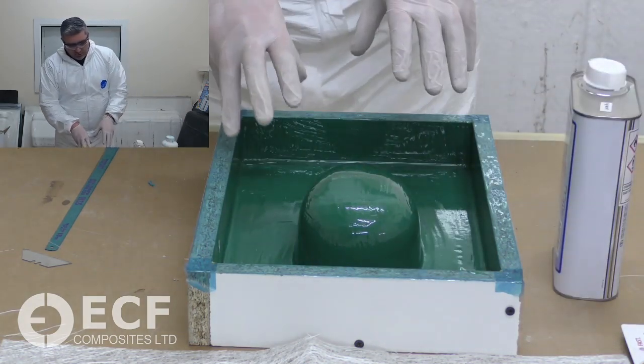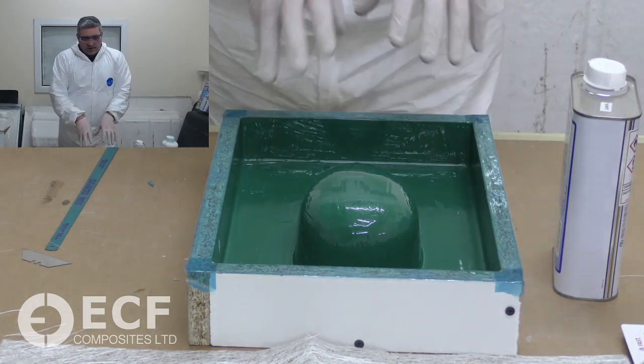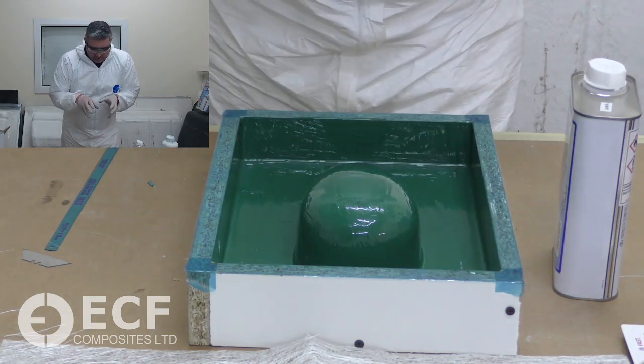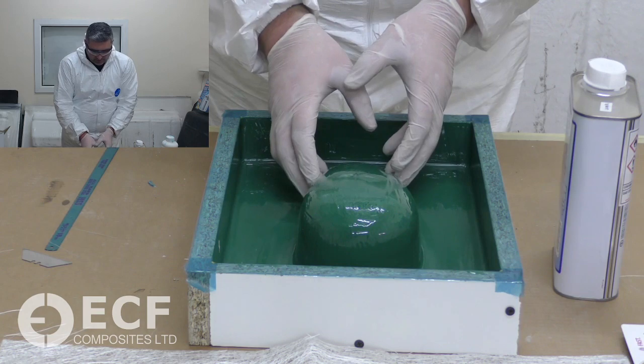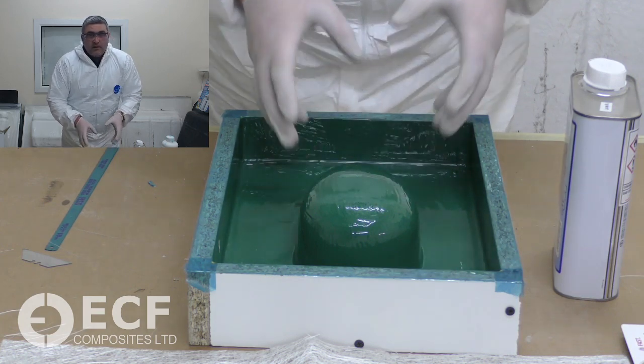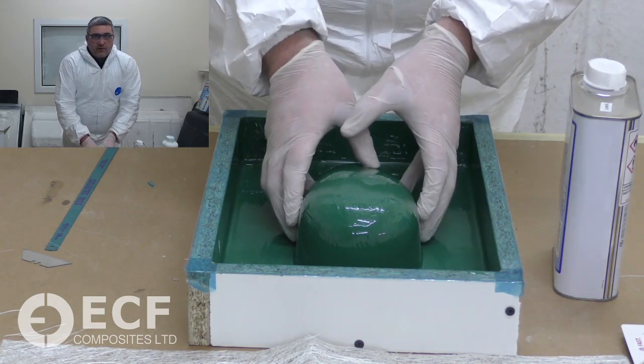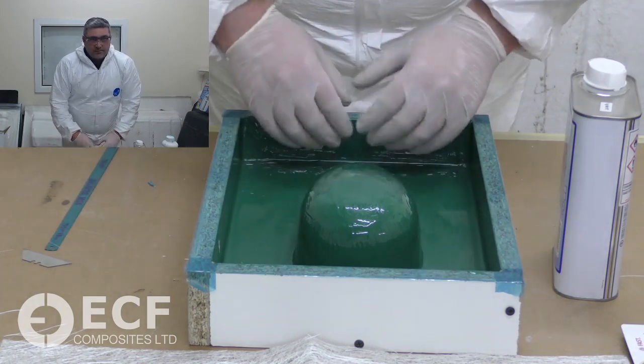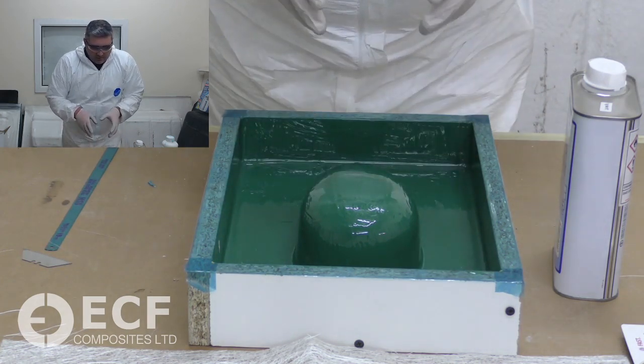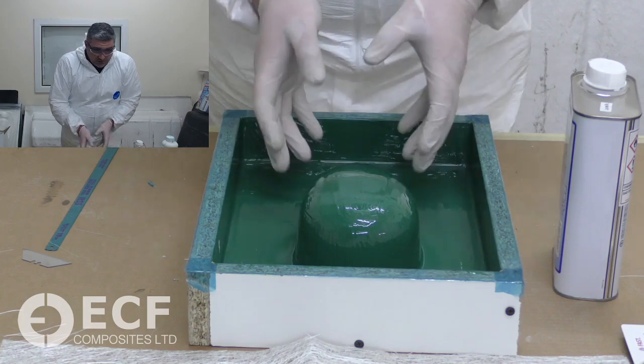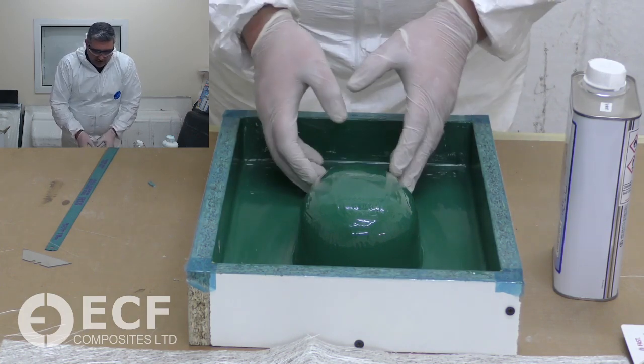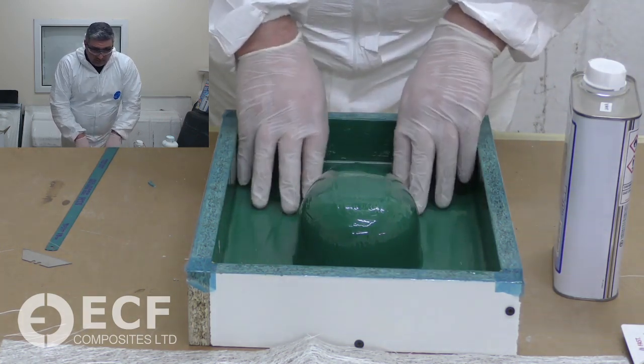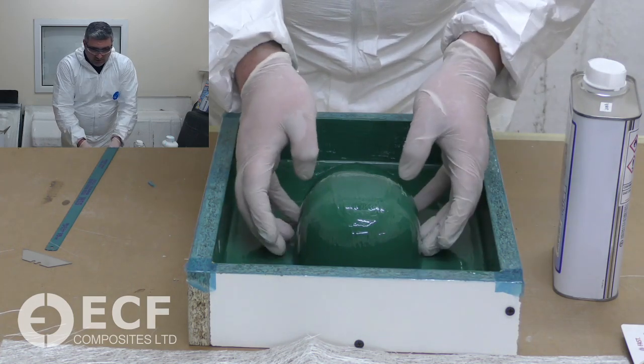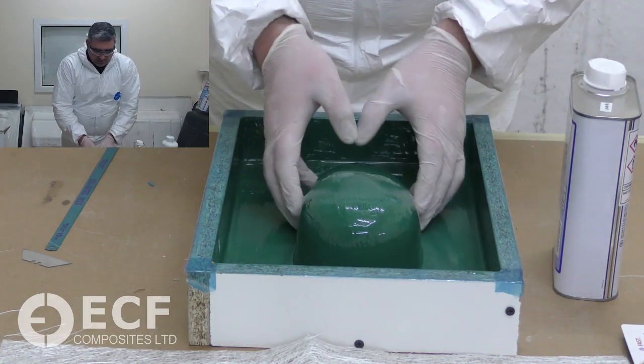The other reason we're going to just do one layer is we want that one layer to cure off. We want to get the fiberglass fully consolidated, we want to get all the air out, and we want that to cure off so that when we put the other layers on to beef the mould out, all the actions we're using are not disturbing that first layer and pushing air in. We want to be confident that that first layer has good consolidation of the gel coat. That's your critical layer.